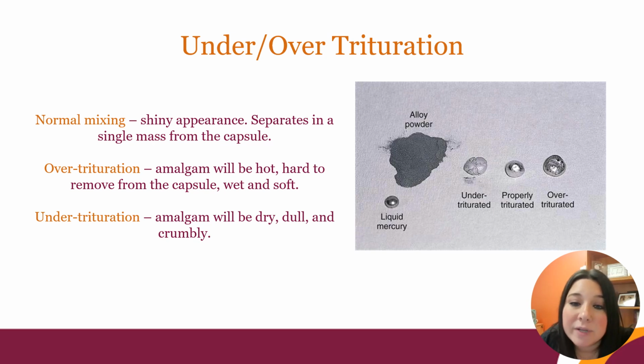So as you can see in the picture here, that alloy powder and that liquid mercury are what are in the capsules. When they're mixed together, they're combined. And then that next area, under triturated, very dry, dull. You can see it breaking apart even. In the middle, you have the properly triturated, so it's nice and shiny. It's one fluid little circle, looks pretty smooth as well. And then in that over triturated, the very last one, it just looks a little bit dull, but also just softer. Like it's not a perfect circle, just doesn't look normal.